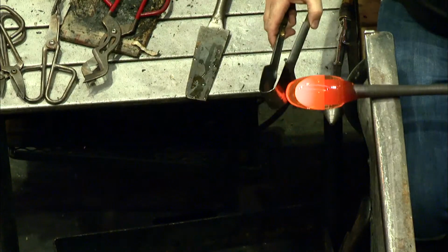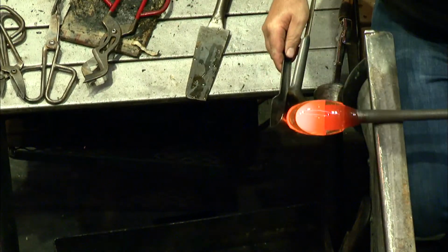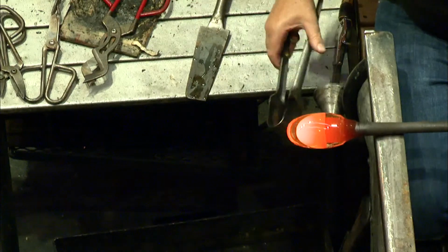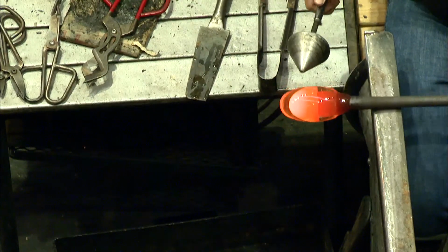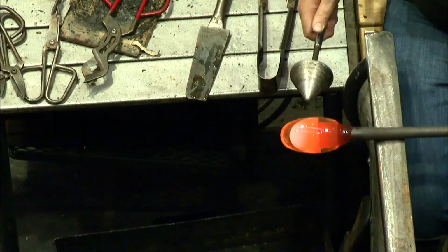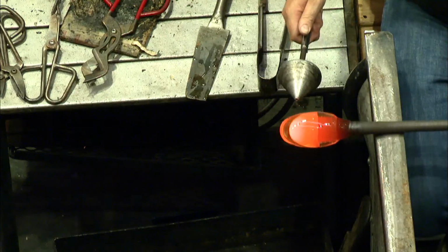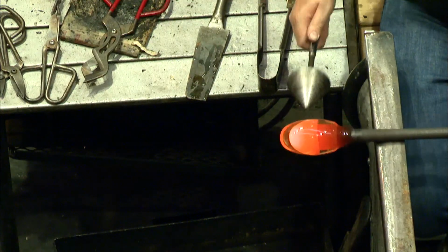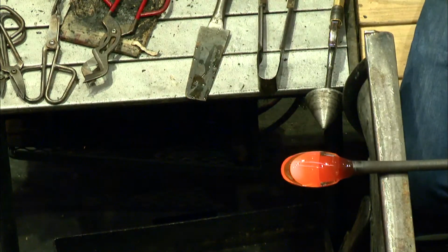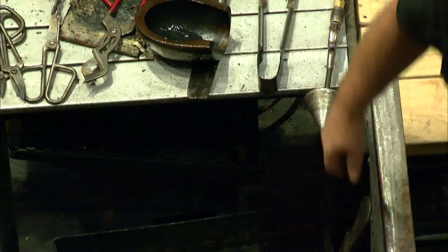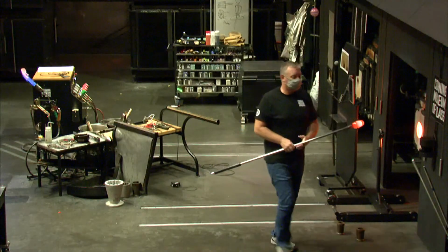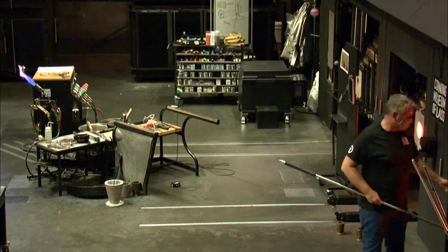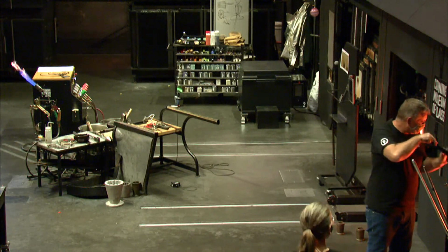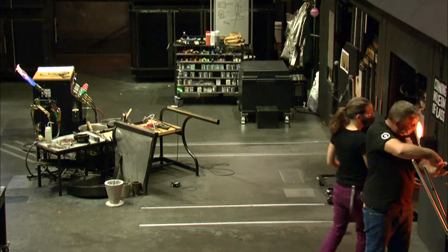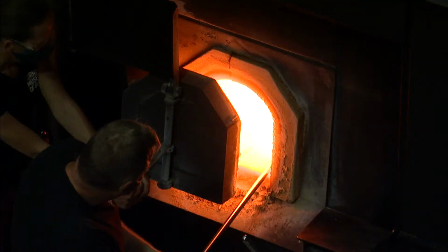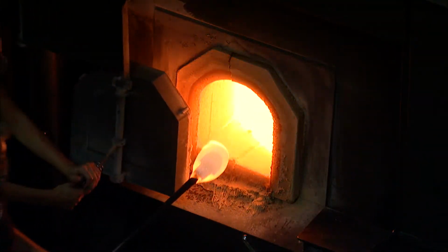And that really depends on what we've been making throughout the day. If we've been making all paperweights all day long, we won't see those come out until a couple of days later, because it can take up to 24 hours to relieve the stress in a softball-sized paperweight. For blown objects that are very thin, such as ornaments, it could take only 8 hours to cool down to room temperature. So it's all just about the thickness of the glass itself.